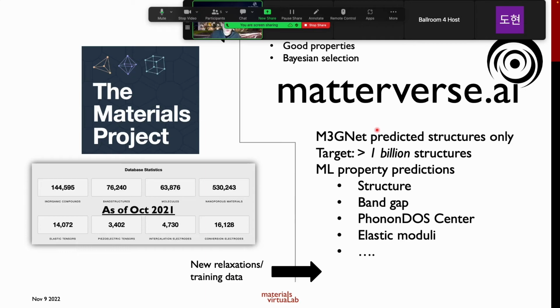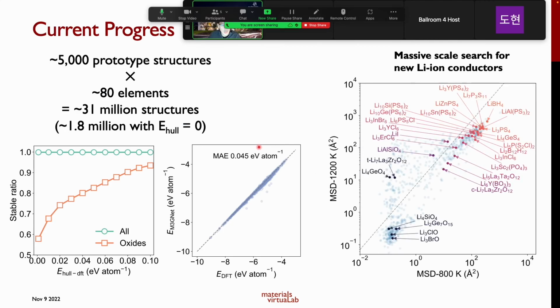Now, we have already begun to use this M3GNet universal potential to build what we call the Matterverse.ai database. This is a complementary database to the Materials Project. The Materials Project will still remain a DFT-based database. For Matterverse.ai, what we envision is a machine learning based database. We are using M3GNet to predict relaxed crystal structures. Our target is, instead of just 140,000 materials, to generate millions and billions of materials. We also would include machine learned property predictions. Currently, we have already generated about 31 million structures, out of which about 1.8 million have an E above hull of 0.